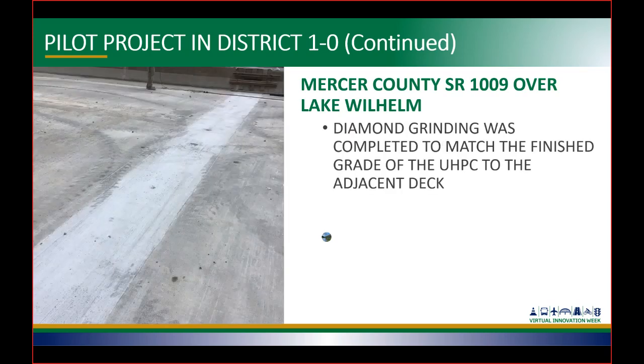And then the next photograph, this is what the finished UHPC joint looks like after the diamond grinding has been completed. The diamond grinding is kind of a tricky operation. It's kind of an art to make sure that you're not going down into the adjoining bridge deck, but the contractor actually did a pretty good job on this, making sure that we weren't removing any material, that latex material, off the adjoining deck.